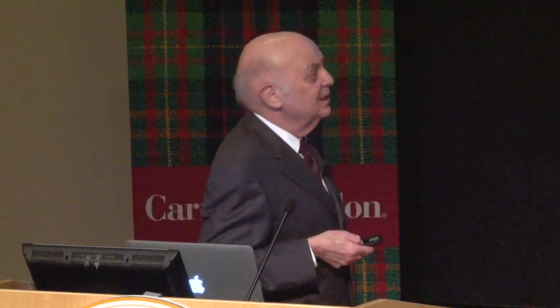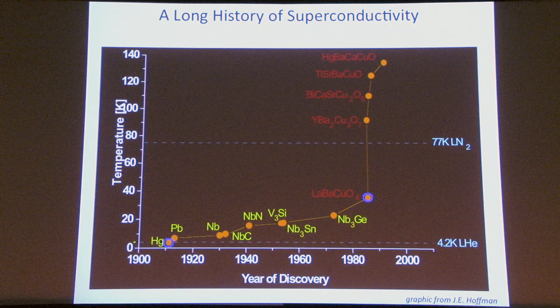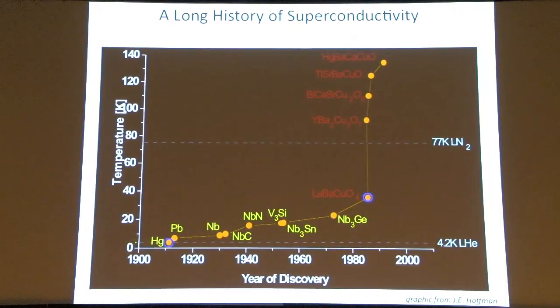And we have a class of materials today that are not understood. So what happened after Onnes was, here's the transition temperature. In the Kelvin scale, if dry ice is about 200, so it's way, way up there. So this is where mercury was discovered, and this is helium. And it climbed at 1/3 of a degree per year, the highest temperature, and sort of sat around in this range of about 20 degrees. And then in 1986, 87, the superconducting copper oxides were discovered, and they're much, much higher, in fact, above liquid air temperatures.